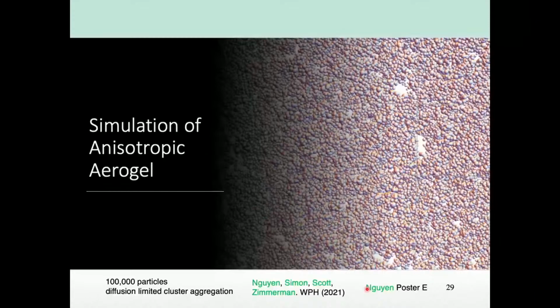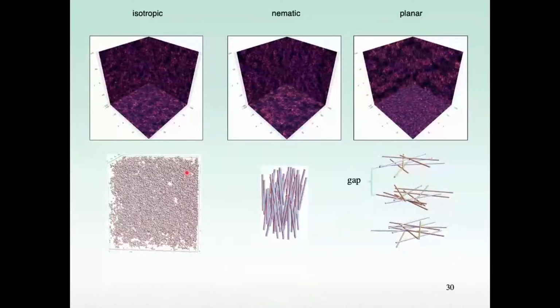I'm going to tell you a little bit nonetheless, and that is from the calculations over here on the left at the bottom. Take a look at that. This is a three-dimensional view of 100,000, this may be 40,000 actually, silica particles that have diffused and aggregated. And you can project in either the XY plane or the XZ or YZ planes what that looks like. And if you do so, you see for an isotropic aerogel, that is where the time steps are the same in all three directions, more or less the same thing in each of these faces.